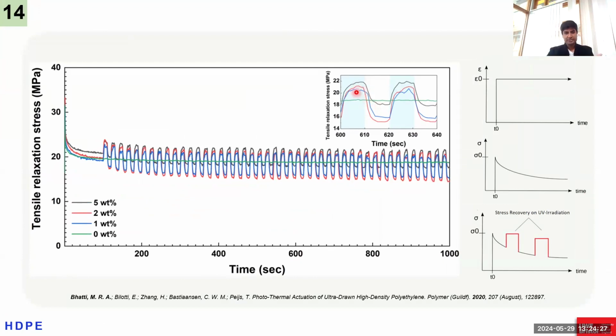So your question is why this happens. We have to consider the polymer at the polymeric level, the chain-oriented level. What does polyethylene consist of? Polyethylene consists of a crystalline region and an amorphous region. When we orient these polymers, the amorphous regions are converted into crystalline regions, and the crystallinity of the polymer increases. Whether we are talking about high density polyethylene at a draw ratio of 15 probably, or ultra high molecular weight polyethylene at a draw ratio of 60 or 80,